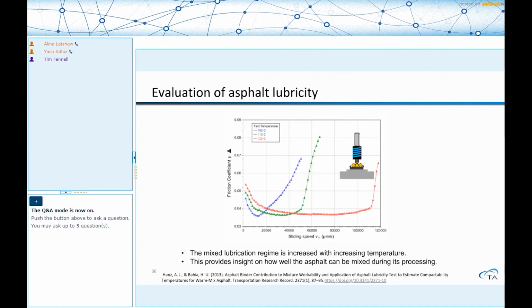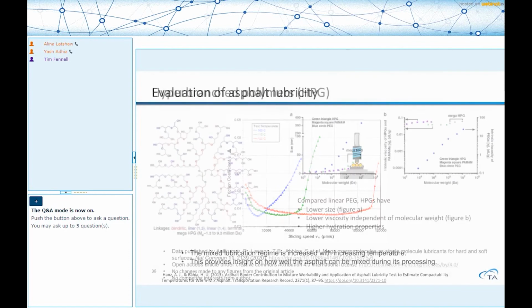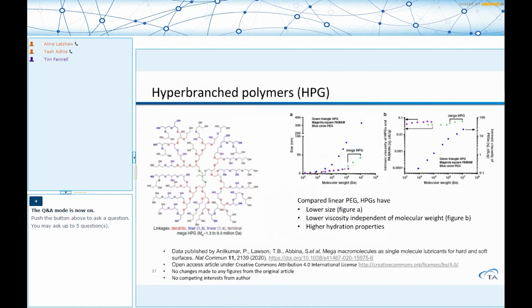So at 100 degrees Celsius, at 20,000 micrometers per second, the friction starts increasing. But at 120 degrees Celsius, the friction is more or less not constant, it's decreasing, but it doesn't start increasing until orders of magnitude ahead. And so this gives you a very nice idea about how the different additives that are added in this particular asphalt mixture to improve its processability is hyperbranched polymers.